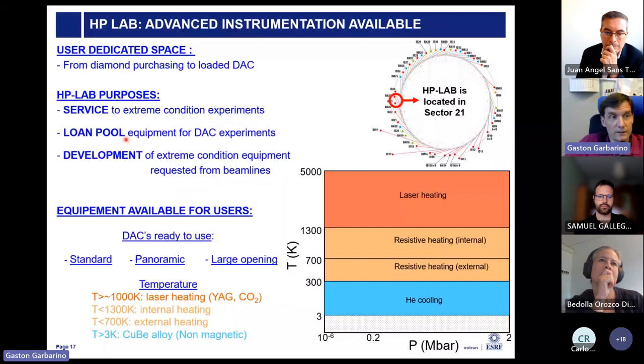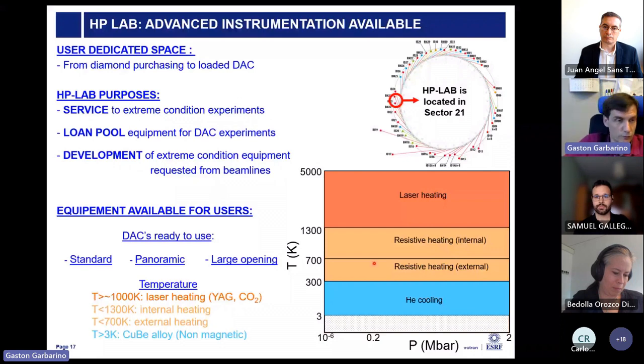So we can loan equipment, diamond anvil cells. We can at the same time develop some particular activities or specific diamond anvil cells or equipment to be able to adapt for particular experiments. Nowadays, with the equipment that we have, we are able to reach 2 million atmospheres in the lab and temperatures as high as 5,000 Kelvin or in excess of this, depending on how the sample couples with the laser, and to cool down to something like 3 Kelvin. And all this we can move inside the lab the way we would like.